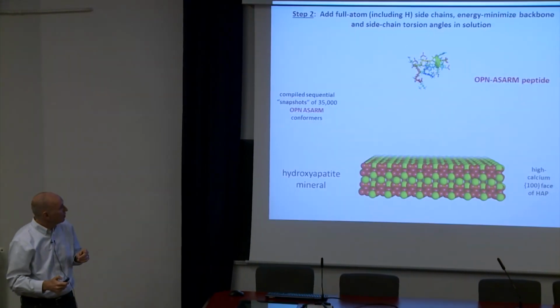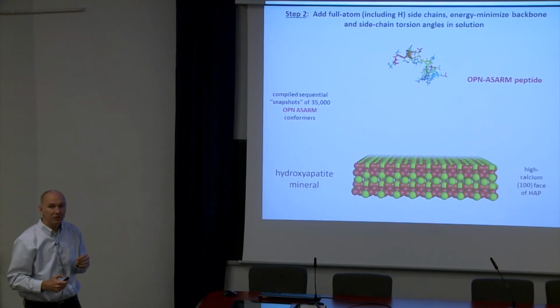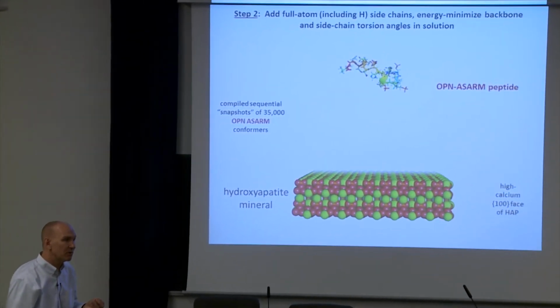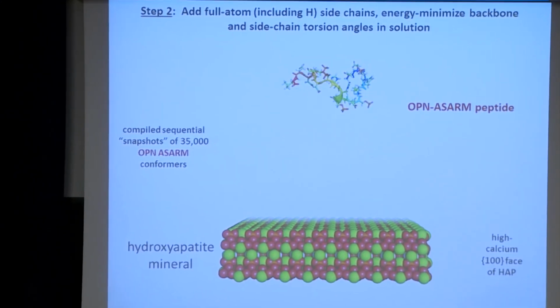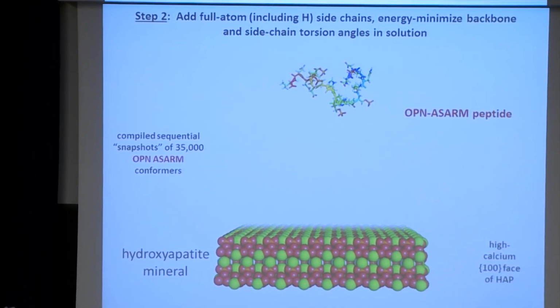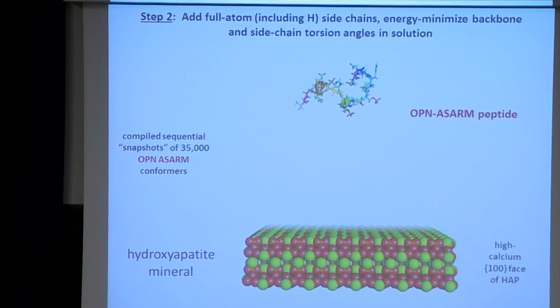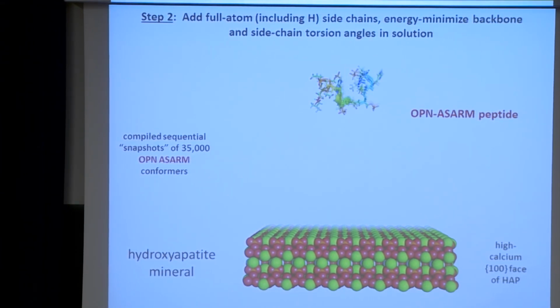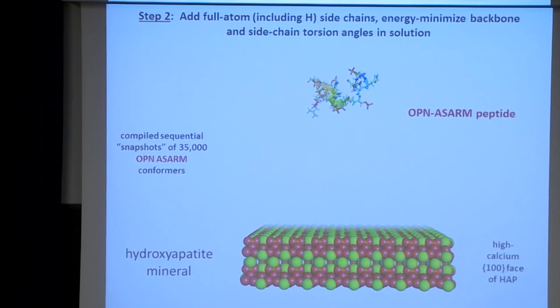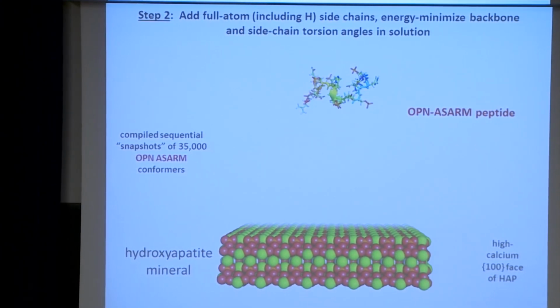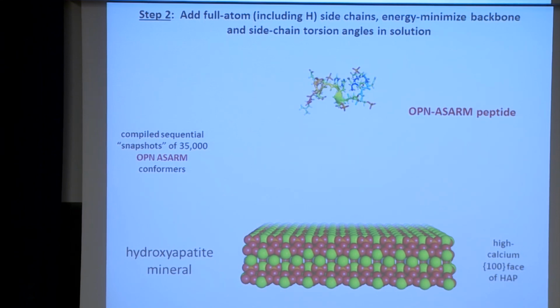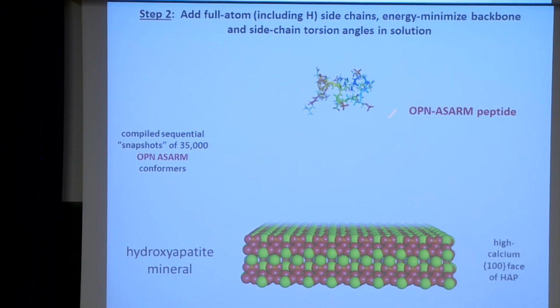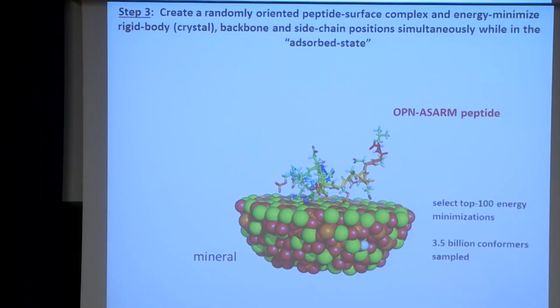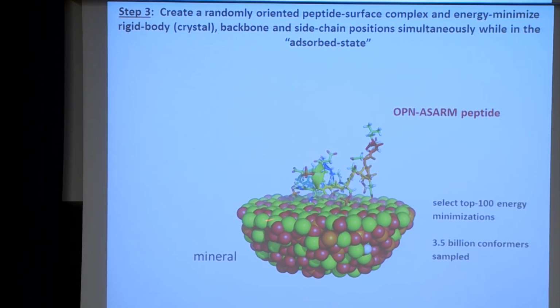And what he did was dock in low energy, this is energy minimization, supercomputing, peptide low energies, and he was able to throw in a constructed slab of mineral. It's a very nice, powerful tool, validated again, as I told you. You build and find your low energy states, and you actually sample 3.5 billion conformers by supercomputing over a span of a few days, for a peptide this size, an 18-mer. And you find how this peptide docks and finds its low energy states on a constructed slab of hydroxyapatite.